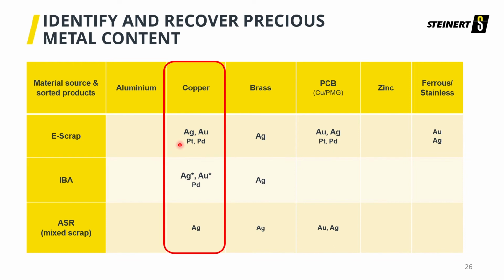Of course, there are exceptions to any rule, but here are some of the common precious metals that you look for and see in the different incoming streams of E-scrap, incinerator bottom ash, IBA, or ASR. And we're going to focus on just this copper fraction that's highlighted. So for E-scrap, you see, of course, the silver and the gold and platinum and palladium. This is a lot in, you see this in your board content, you see this in copper coatings, and this is very common for E-scrap.